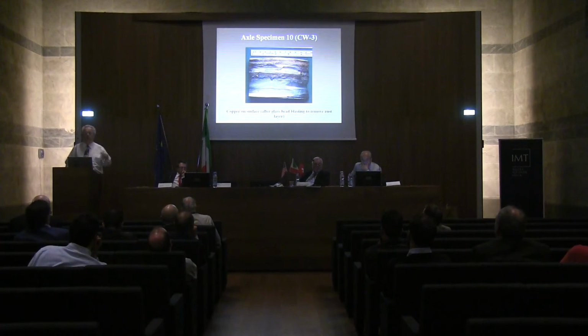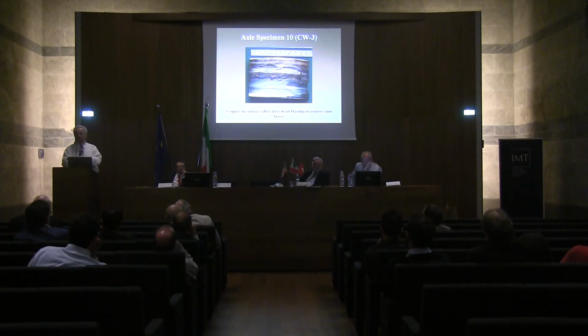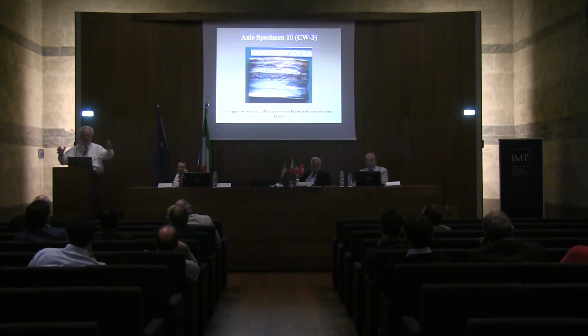The 2 axles we first got from Seaboard, I took down to the Bethlehem plant and we did X-ray analysis looking for the cracks with a powerful X-ray unit for crack detection that they had in the foundries there. They don't exist anymore. And you could see cracks coming in the surface all over the region below the fracture, anywhere it was underneath the friction bearing, which was like 1 meter long.